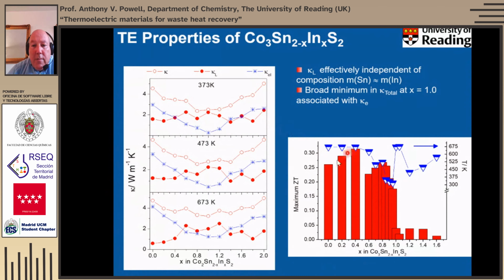So the net result of that is we get quite promising figures of merit before we get to that 50-50 composition. We're reaching 0.3 at our maximum point here, and that's at about 675 Kelvin. But as we get closer to that 50-50 composition, they start to decrease, and then it falls off a cliff edge, and we get very low figures of merit in that second metallic region.